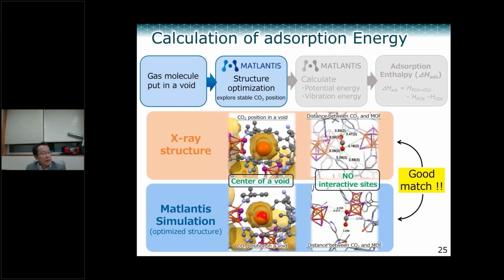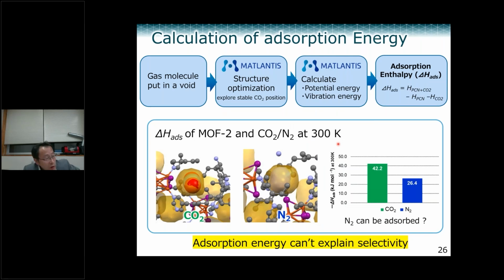Then we calculated the absorption energy. First of all, the CO₂ case: 42.2 kilojoule per mole, and the dinitrogen case: 26.4 kilojoule per mole. From this result, actually we cannot explain the selectivity of this material for CO₂ and dinitrogen, right? According to this absorption energy, we should be able to expect some absorption of dinitrogen in this material. However, the reality is we cannot explain that.